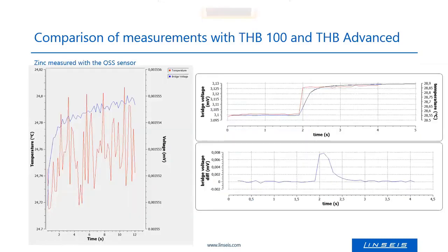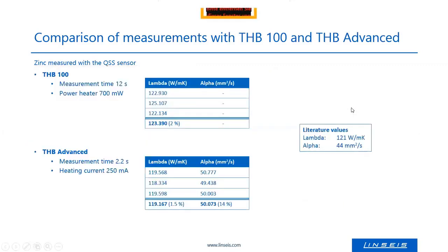Then the next one is zinc. For the THB 100, we are at the limit already. Originally, the THB 100 was specified up to 100 watt per meter Kelvin. That's the reason why it was called 100. And zinc is above 100 watt per meter Kelvin. And you see the measurement curves are quite noisy, so the error is probably very high here already. And with the new one, the advanced instrument model, we can reach quite a nice curve.